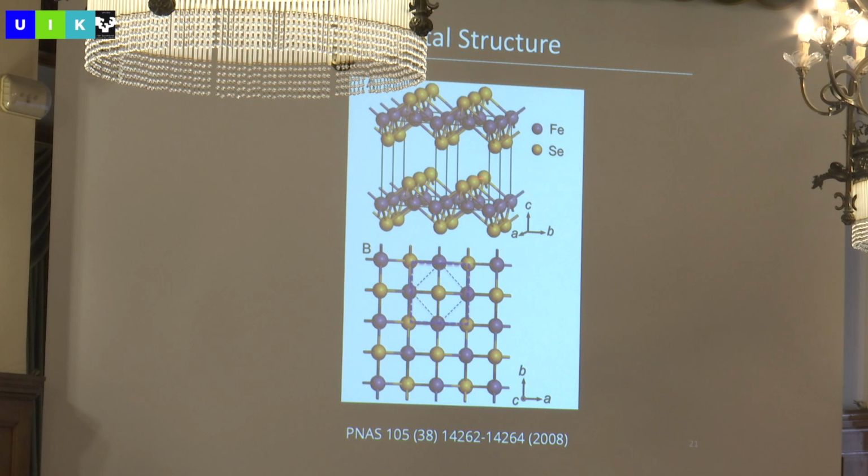One thing I want to point out is that in a given crystal, let's say this is the top selenium, whether these top seleniums occupy this position or the equivalent position here is a choice made by the crystal. So you can imagine that in a given crystal, you might have areas that look like this and areas where this is entirely flipped upside down, okay? That'll give you a domain wall.